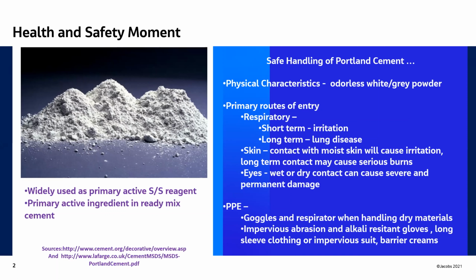So because it's a powder and because it's strongly alkaline, there are a number of issues associated with this that are primarily skin contact and respiratory if you inhale that. And so at that pH, you begin to dissolve mucous membranes. And so the main concern here is that you'll get this in your eyes where it will burn and be an irritant. Respiratory, it also contains silicates, crystalline silicates. So there's concerns about that.